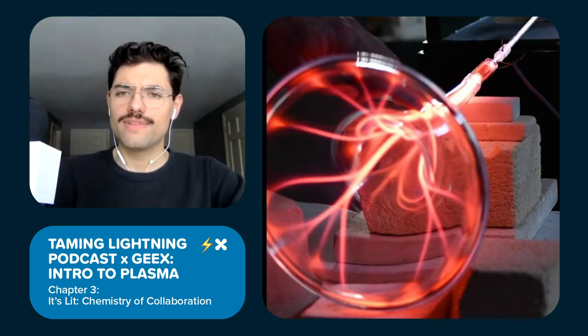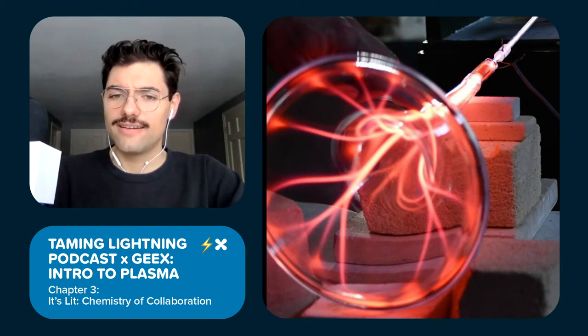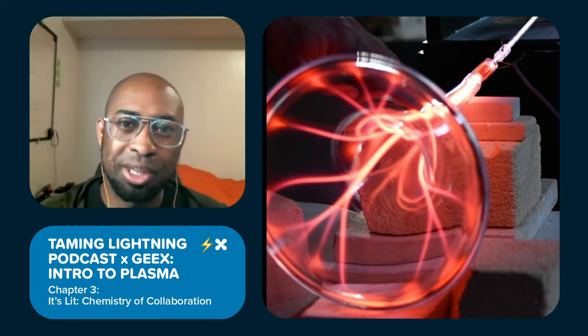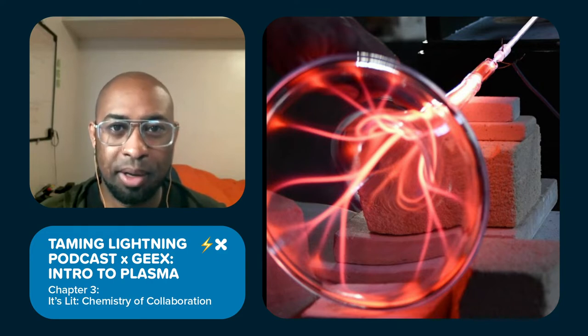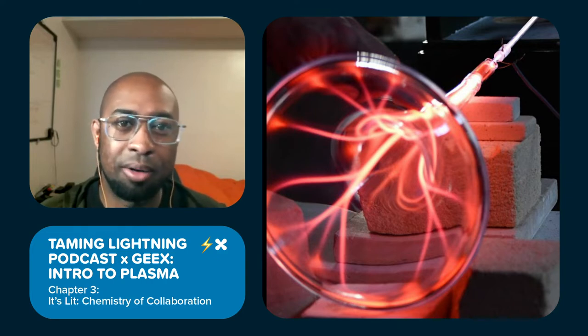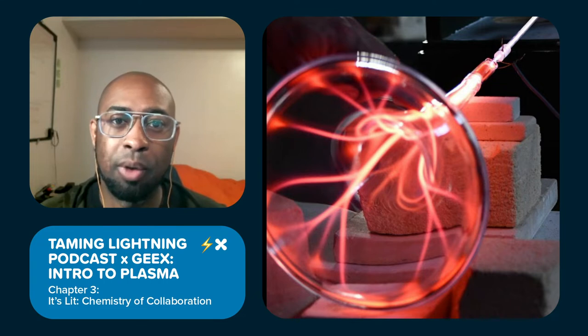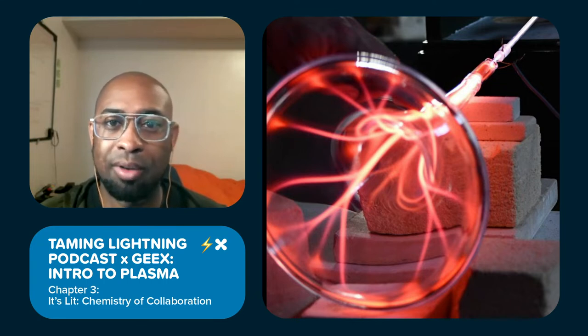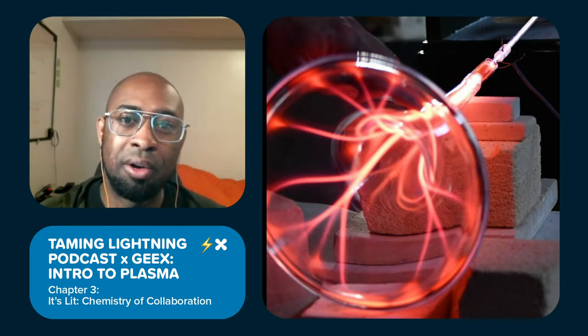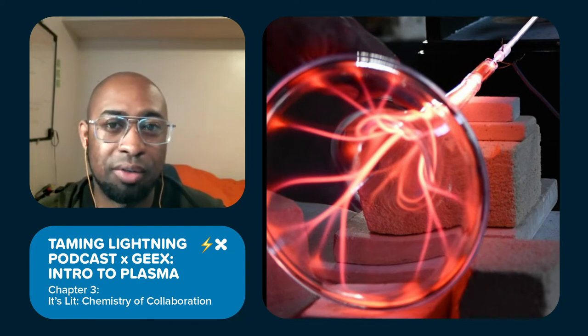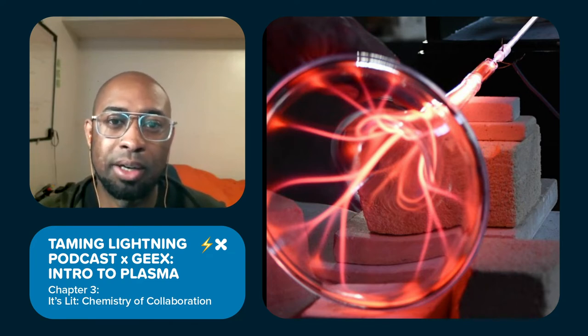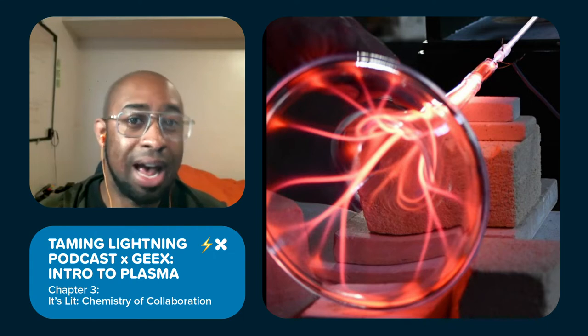So once I'm happy with the gas fill and the effects I have, what are the final checks I should be making before I tip off the vessel from the manifold? Well, number one is you want to be satisfied with your fill visually. Make sure that you have adequate power to your transformer. You want to make sure that shocks aren't coming from the vessel when touching it, which is an indicator of too much power. You don't want it to be too dim, which means you don't have enough power.